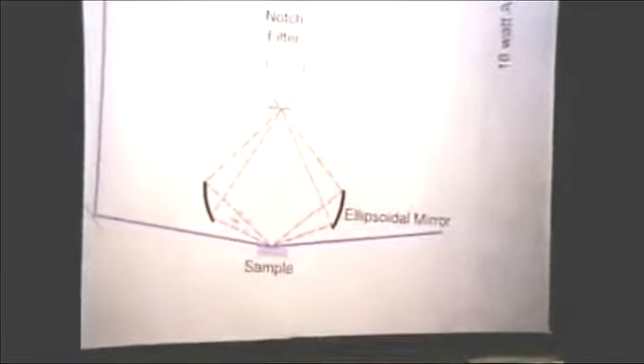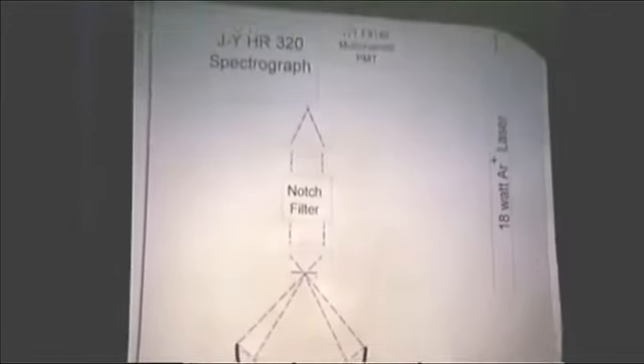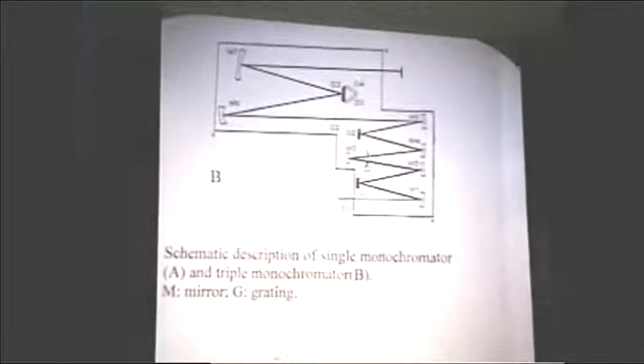And so this just shows the same instrument again. The primary thing that we needed to do was to get rid of this filter that we were using to remove most of the elastically scattered light from the sample. So the way to do that is to use a different spectrometer. And the type of instrument that we need and that we actually now have is a 3-grating instrument.